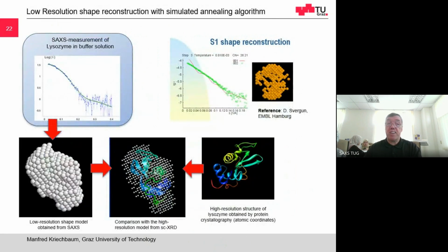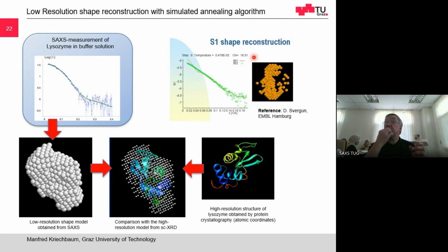So what does this mean? Here you have your experimental scattering curve, and then you try to find in the real space a model which fits your experimental scattering curve. So the red curve is a corresponding scattering curve, and the green is your experimental. Then in that case, you end up with an elongated particle, because this red curve fits the green curve. You have to search a model in the real space which fits your scattering curve in reciprocal space.